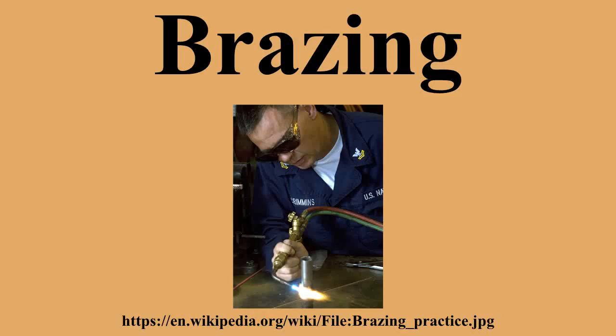Noble gas, non-oxidizing, more expensive than nitrogen. Inert parts must be very clean, and the gas must be pure. For copper, silver, nickel, copper-phosphorus and copper-zinc filler metals. For brazing copper, brass, nickel alloys, low, medium and high carbon steels, chromium alloys, titanium, zirconium, hafnium.